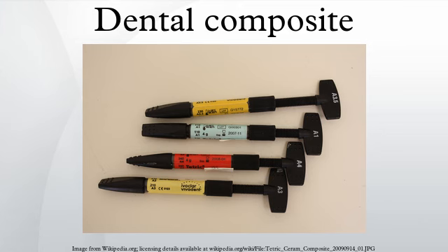According to a 2012 review article by DeMarco et al. covering 34 relevant clinical studies, 90% of the studies indicated that annual failure rates between 1% and 3% can be achieved with Class I and II posterior, rear tooth, composite restorations, depending on the definition of failure and on several factors such as tooth type and location, operator, dentist, and socio-economic, demographic, and behavioral elements. This compares to a 3% mean annual failure rate reported in a 2004 review article by Manhart et al. for amalgam restorations in posterior stress-bearing cavities.